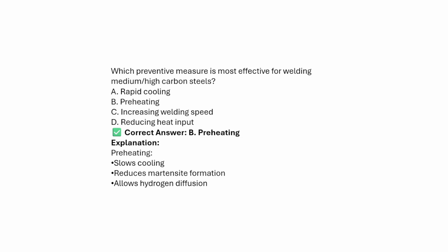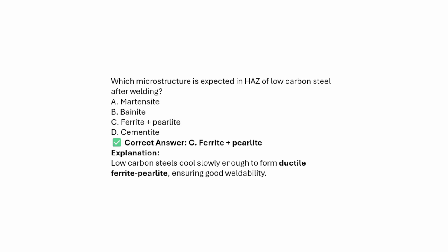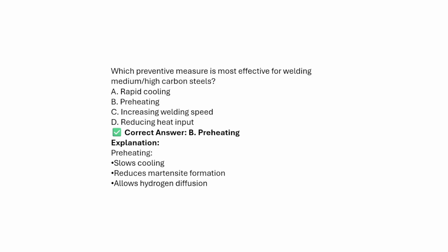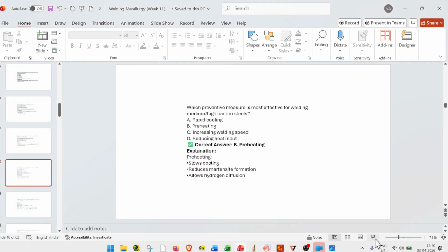So how can we reduce the cooling rate? By providing preheat treatment. By providing preheat, we slow the cooling, reduce the martensite formation, and allow the hydrogen to diffuse out. Okay, and in comparison between medium and high carbon steels, we have to provide more preheating for the high carbon steel compared to the medium carbon steel.